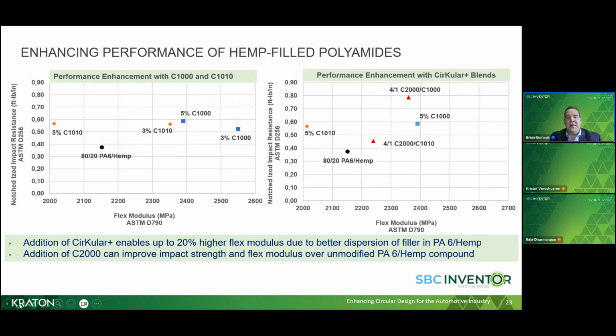But what we did is we evaluated both of our compatibilizer and performance enhancement series Circular Plus additives that Raja mentioned earlier into an 80-20 hemp-filled compound. And depending on the loading, we saw impact performance improvements of 25 all the way up to 100%. But if you take a look at the flex modulus, the addition of Circular Plus shows up to 20% higher flex modulus, so stiffness, due to improved interaction between polyamide and hemp fibers aided by the Circular Plus modifiers.